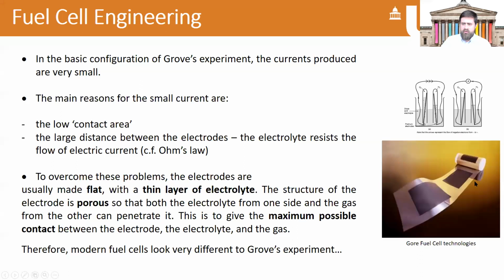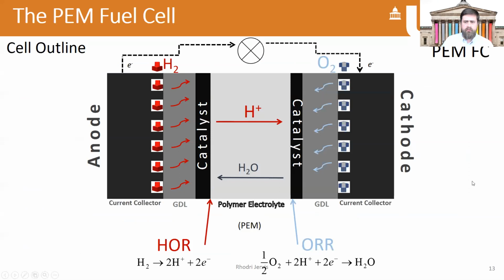But there you can see in the picture on the right-hand side of what a modern fuel cell actually looks like, the working part of a fuel cell. And it's essentially a very thin sheet of plastic, it's quite special plastic, and as I say, we'll talk about it in a second. And on top of that, you've got printed these electrodes. So instead of very flat metal surfaces, you've got electrodes that contain very high surface area metal nanoparticles. And that means that we can get a huge amount more reaction happening per second. And the more reactions you have, the more electrons are given off in these electrochemical reactions. And therefore, the more electrons you have per second, the higher current you have, okay? The higher electrical power. So modern fuel cells look quite different.